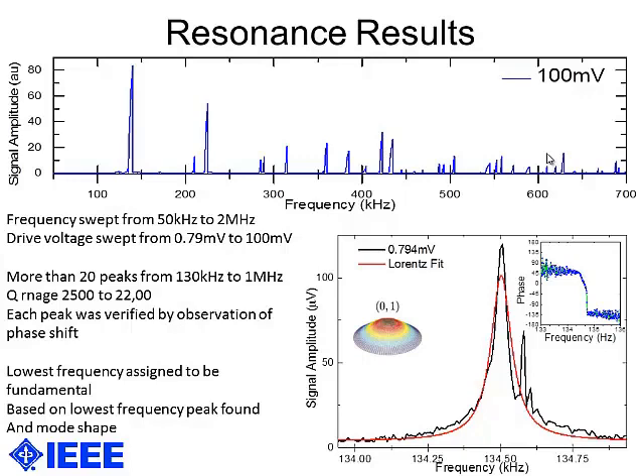Shown here on the bottom right is the lowest frequency peak, which we assigned to be the fundamental mode. We based this on the fact that we did some mapping and found that the highest amplitude was roughly in the center, with decreasing amplitudes towards the edges, as is expected of the fundamental mode shape, and it was also the lowest resonance peak frequency that we could find.